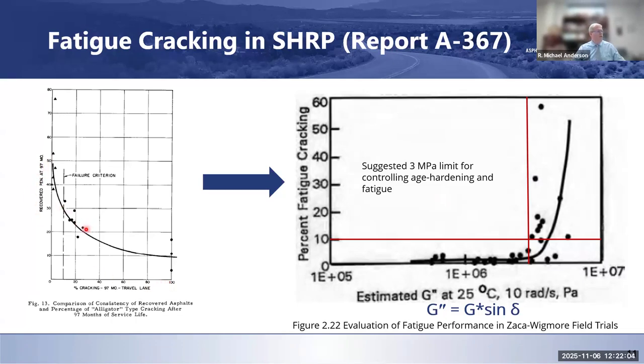And then they fit this curve through it. And where they were looking at 10% cracking, this is kind of their failure criterion. That's how they established what that recovered penetration value was. Well, in the figure over here, they took those penetration values, converted them over to G star values and G star sine delta values, and looked at the same 10% criterion, and instead looked at what a proper limit might be for controlling hardening and fatigue cracking. And they set that originally at 3 megapascals, and that eventually got changed to 5 megapascals, or the 5,000 kilopascals that we're used to seeing in AASHTO M320 and AASHTO M332 for PG binders.